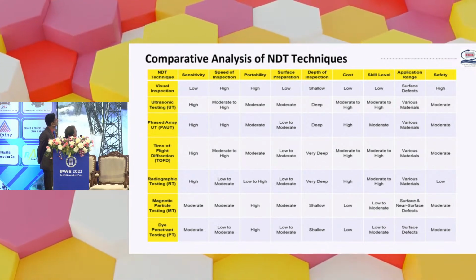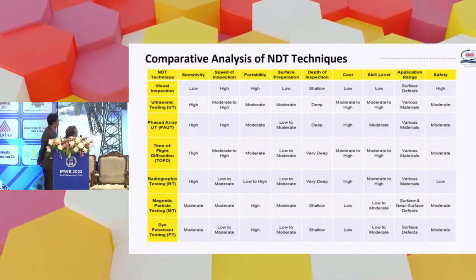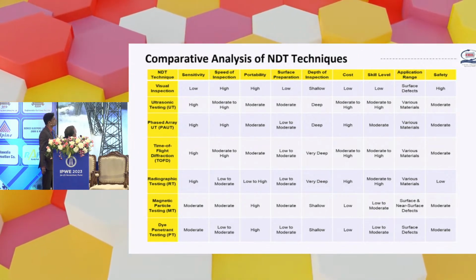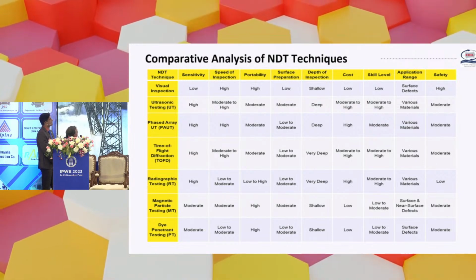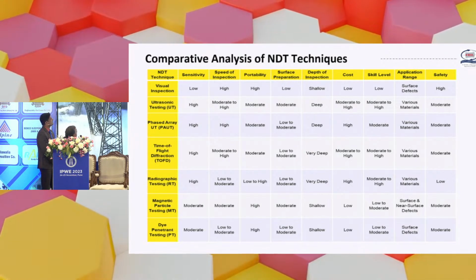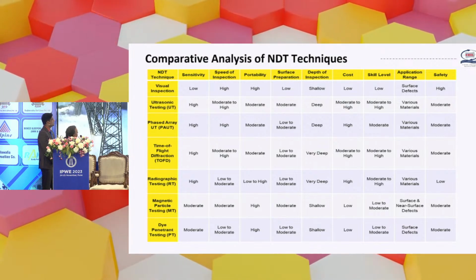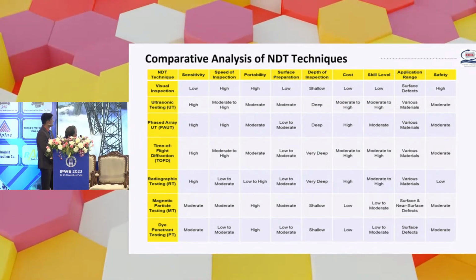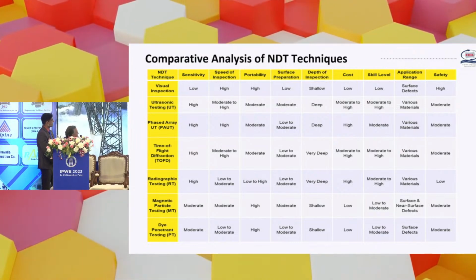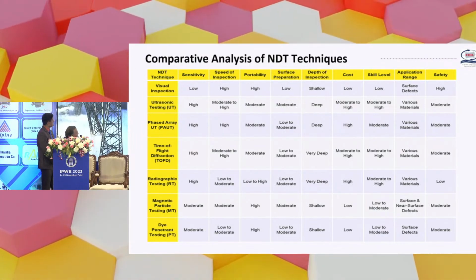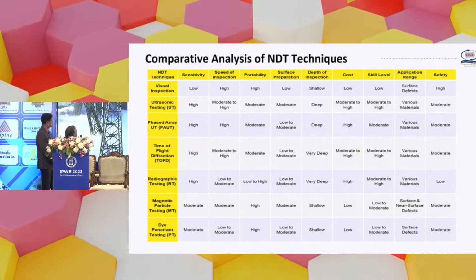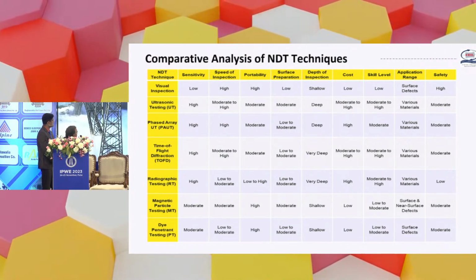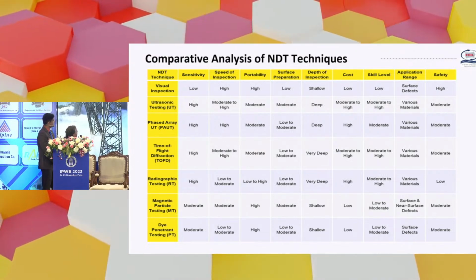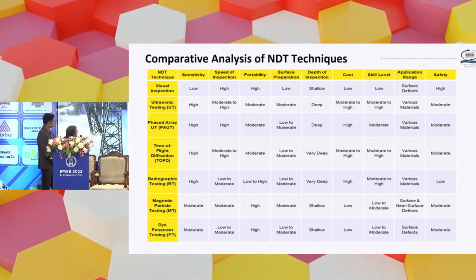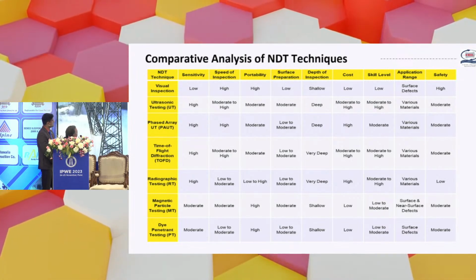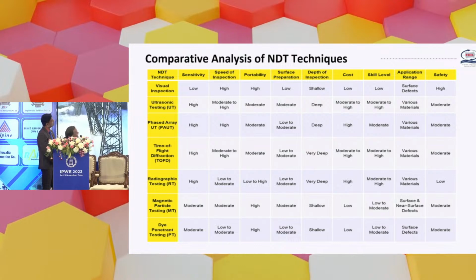The NDT techniques comparative analysis has been put here in tabular form, where phased array ultrasonic testing, which was adopted in the Chenab Bridge, has an advantage over radiography testing, where laminar defects cannot be checked, whereas PAUT can check laminar defects. So our engineers are well competent in interpretation of this. Magnetic particle test and DPT are also carried out for surface and subsurface defects up to 2 to 3 mm, where our engineers are well competent.